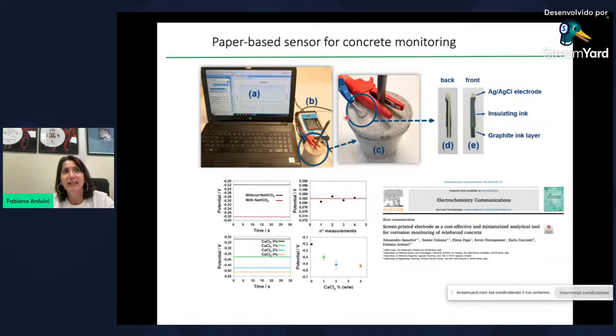In this work, we demonstrate that it's possible to miniaturize the system because we use, of course, the bar, and we use the printed electrode, in this case on polyester, and to close the electrochemical cell, we use hydrogel loaded with KCl. And we demonstrate that it's possible with a really cost-effective system to evaluate the corrosion level of the concrete structure because the potential changes. For example, increasing the chloride content in the concrete, the presence of chloride accelerates the corrosion. We observed a different potential, like in the case of carbonation.